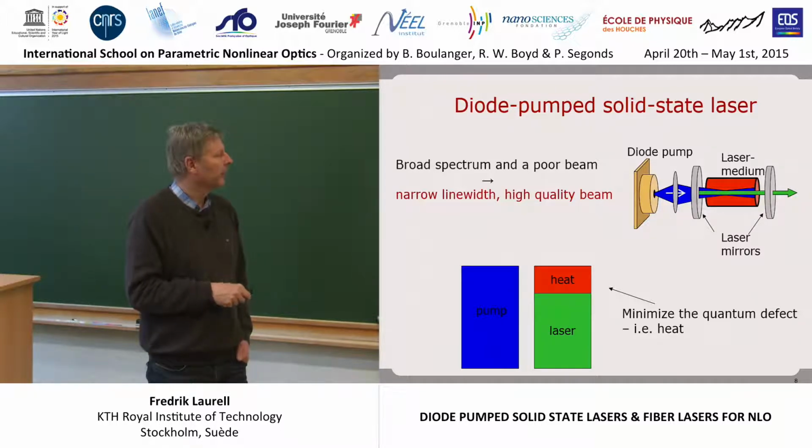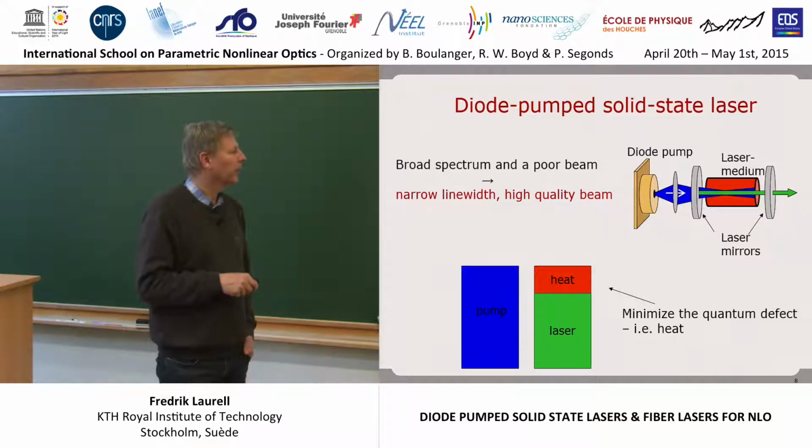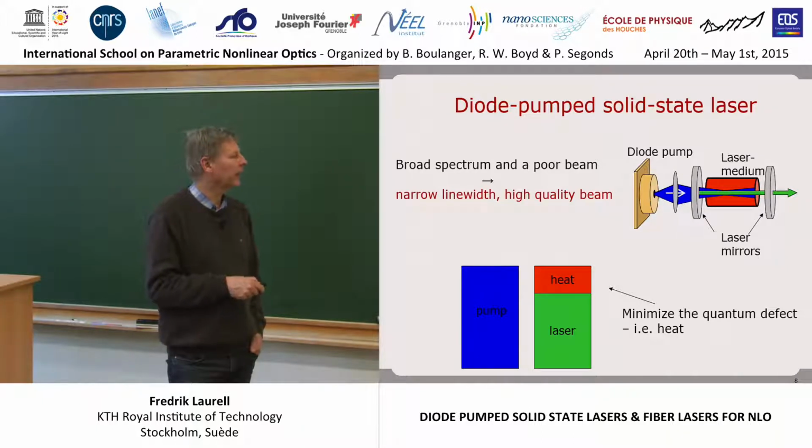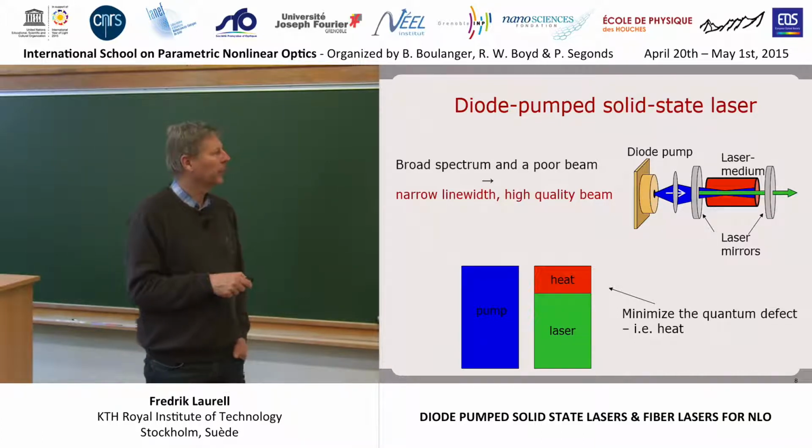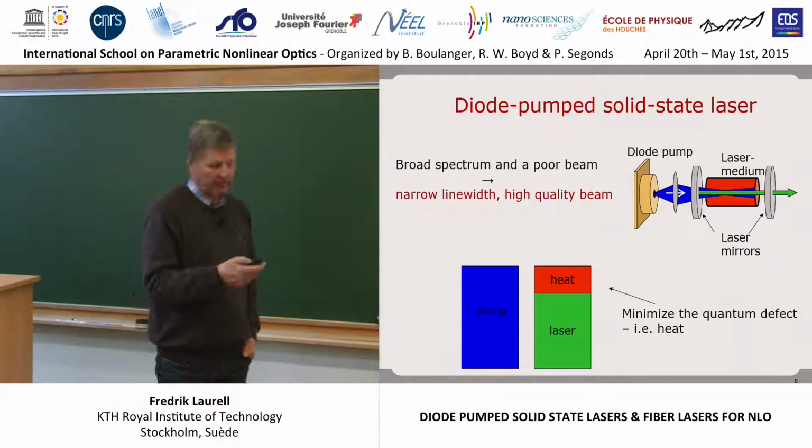And there is a quantum defect, we call it, the heat generated in the crystal. And this one, if we want to scale power here, we have to make as little heat as possible in the laser medium to avoid distortion of the beam.